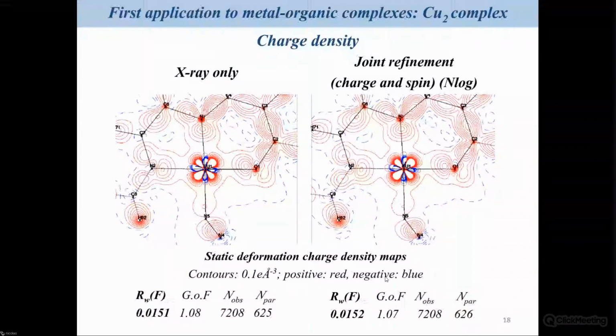Of course, we look more precisely at what we obtained, and especially the charge density distribution around the atoms. Of course, in that case, X-ray diffraction gives you much more information on the system than any other experiment. So it means that the final model should not be really affected by the way that you carry out the joint refinement. And if you observe the distribution of the charge density around the copper atom, you see that the maps are very close if you compare the one obtained from the X-ray diffraction experiments only to the one obtained after a joint refinement. And again, the agreement factors are very, very close.